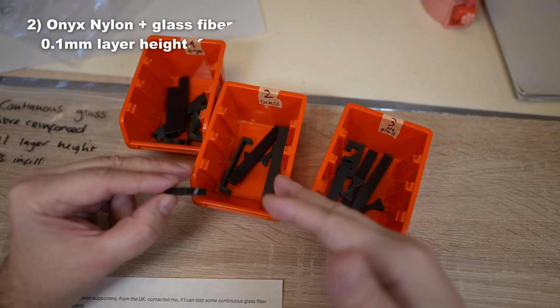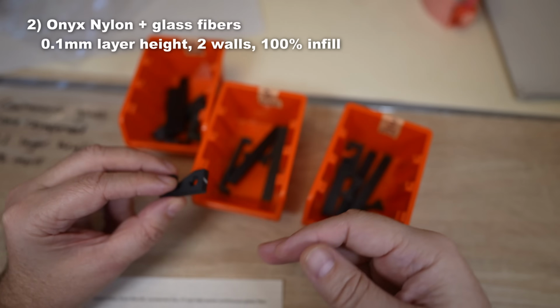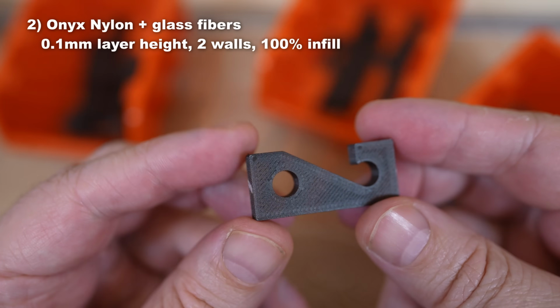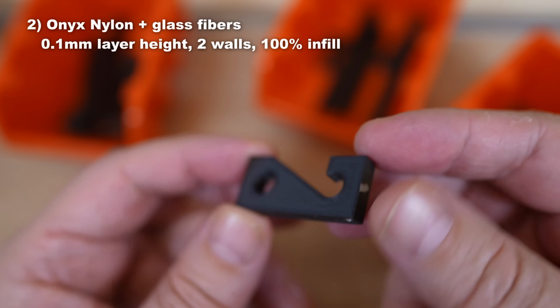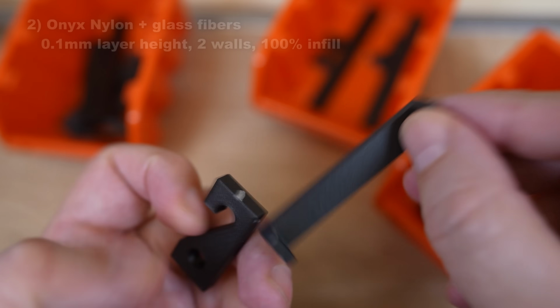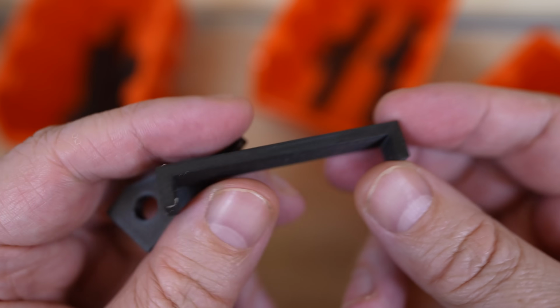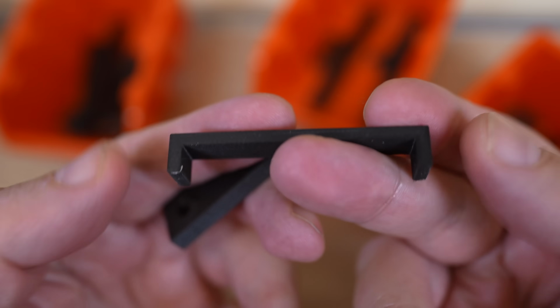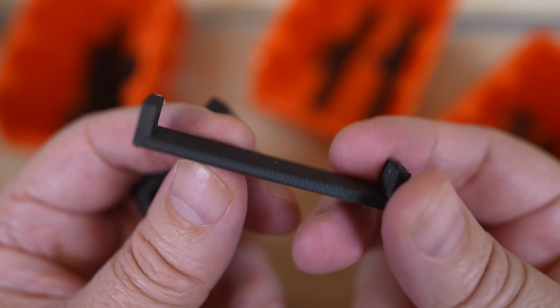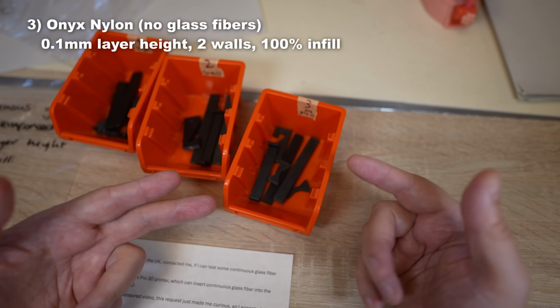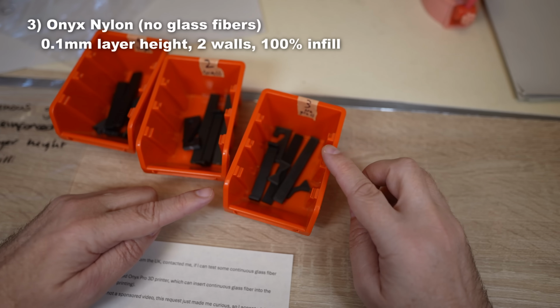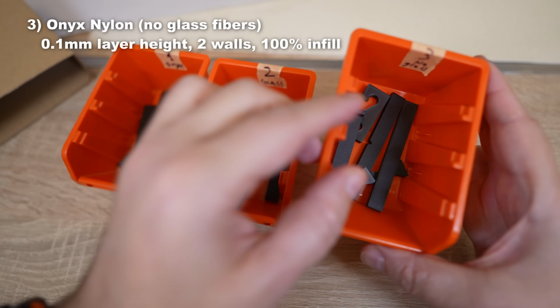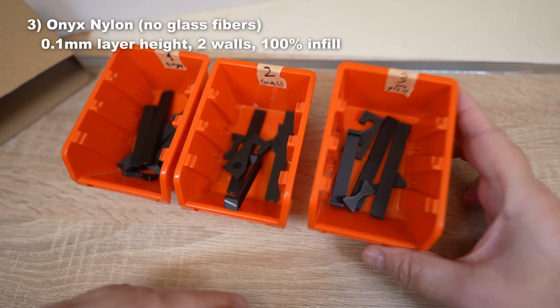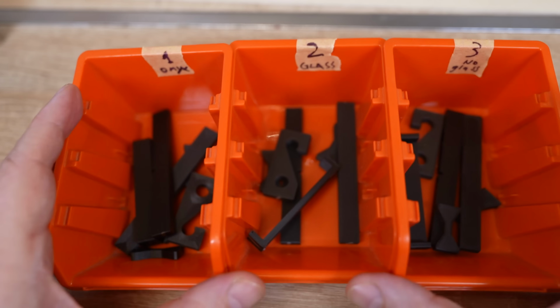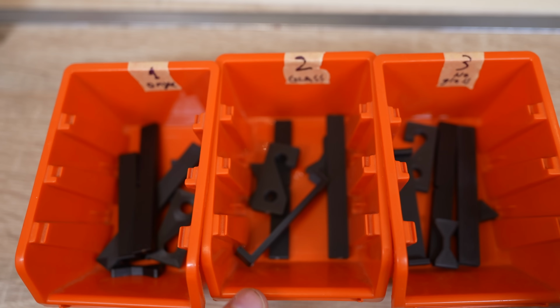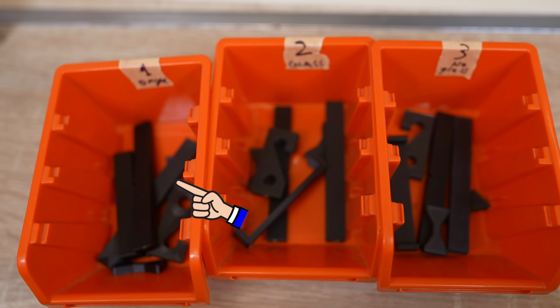The second group is the most important. It is a set of continuous glass fiber reinforced parts with 0.1 mm layer height, 2 walls and 100% infill. Only the temperature test object was printed with only one wall to allow some glass fibers to be in these bags too. The print settings for the third group are very similar to the second one, only the very big difference is that here we don't have those glass reinforced fibers inside. So this will be just for reference, and I'm expecting similar mechanical properties of groups 3 and 1.